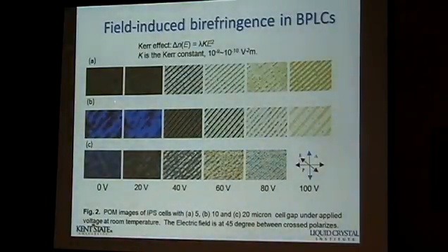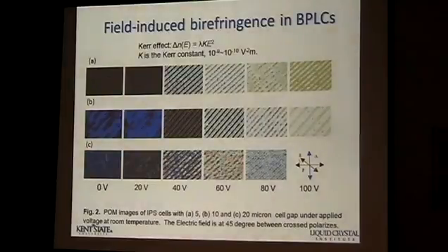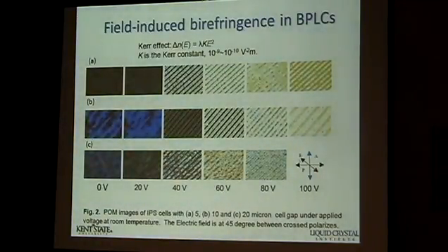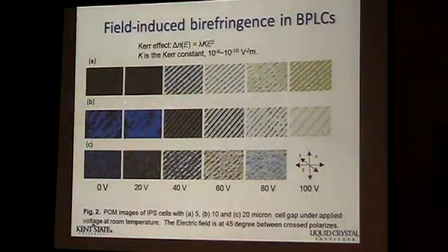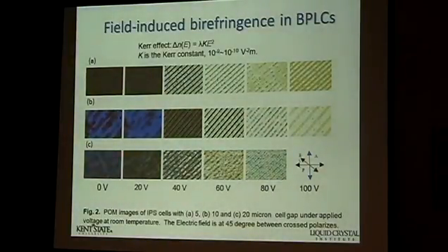So here to show you something. For example, the cell gap effect for 5, 10, and 20 microns over here. You can see 5, 10, 20, and the cell gap effect shows some defect lines, and the defect lines perfectly sit on top of the electrode. The electrode width is about 10 micron. Okay, so the 10 micron pitch, and then you can see that